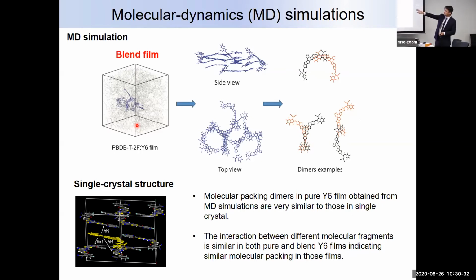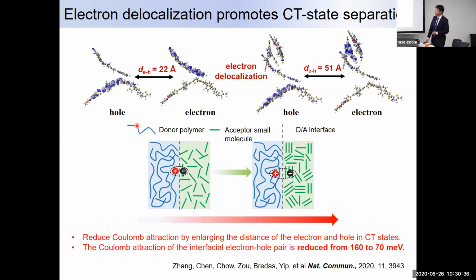We can start to take out pieces of that to do the other calculation, which is the electron delocalization, right, within the donor and acceptor interface. Here, I show you that when we only have a monomer of the acceptor and also the monomer of the polymer, okay? So you can see that this is kind of the charge transfer exciton. The charge transfer distance is only about 2 nanometer.